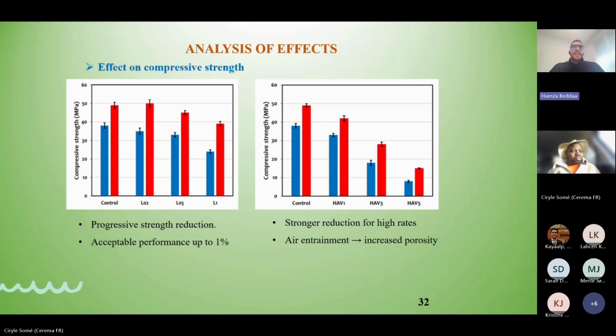However, comparing lignin and waste vegetable oil directly can be misleading by looking at just these two figures, but we need to compare the same percentage. For example, if we take the same percentage for lignin and for oil, which is 1%, we can see that oil shows higher strength than lignin. So they both reduce the strength, but it's still acceptable at a certain rate, which is 1%, for example.